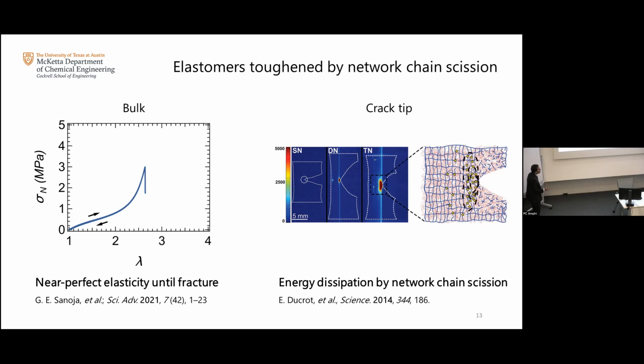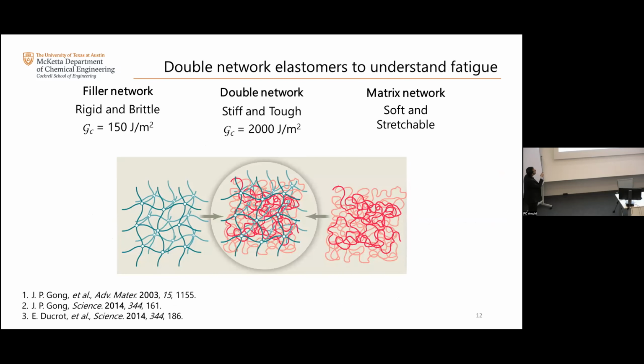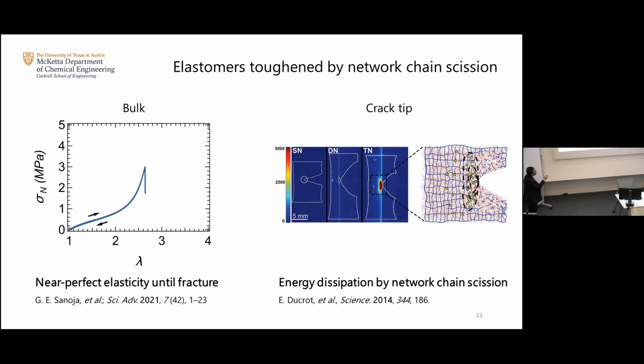And the other neat thing is that it has been shown in this seminal paper, again, coming out of Costantino's group, that if you actually image the crack tip, or if you actually image the bonds that are breaking ahead of the crack tip during crack propagation, what you see is that when you go from a molecular design of only a cross-linked filler network, so basically just network number one, you don't have a lot of damage at the crack tip. Everything is localized. But when you start interpenetrating the networks, you see that your damage ahead of the crack tip keeps growing, meaning that you actually dissipate more energy by damage as you interpenetrate one network with the other.